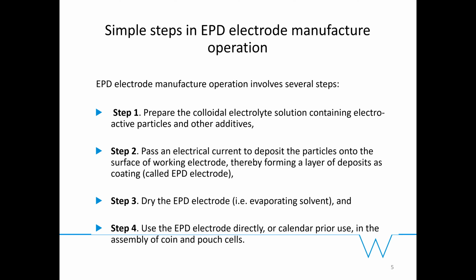Electric current is usually, it says electric current, but you actually need to have almost zero electric current in this case, and usually high voltage, especially if you're using non-aqueous or organic electrolytes. However, if you use water, you can restrict it to 5 volts or so, and you can have a reasonable deposit of particles onto your foil or surface on which you're going to prepare the electrodes.